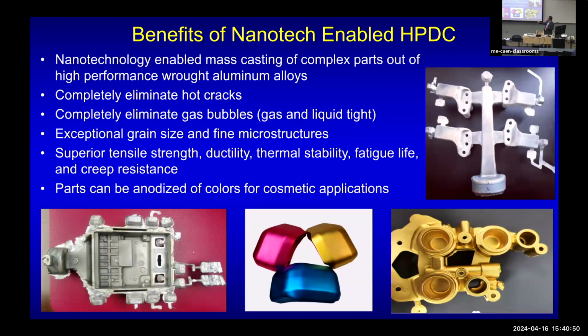And then we almost, I would say, completely eliminate hot cracks. This is one of the big killers for traditional alloys. And also we almost completely eliminate gas bubbles. This allows the die casting component to be welded, right? Can be joined together. Traditionally, the high pressure die casting component is very difficult to weld because there are a lot of bubbles inside. Once you weld, the bubbles just come out, right? They create defects. Right now we can do that.